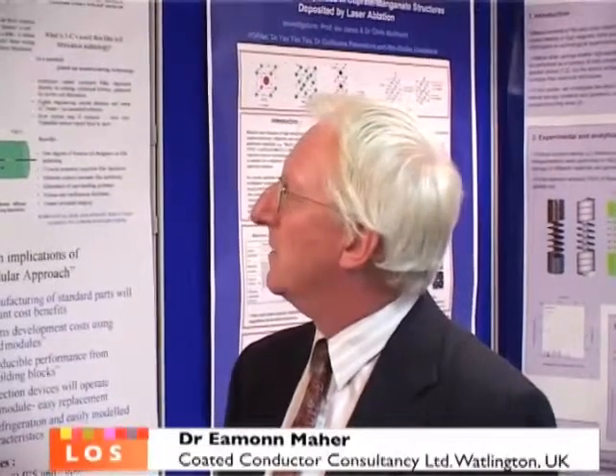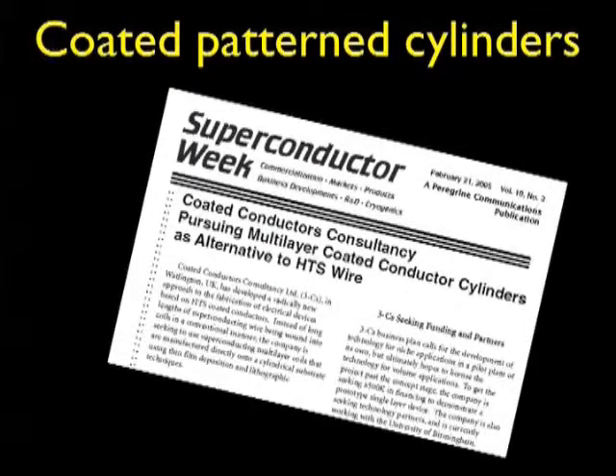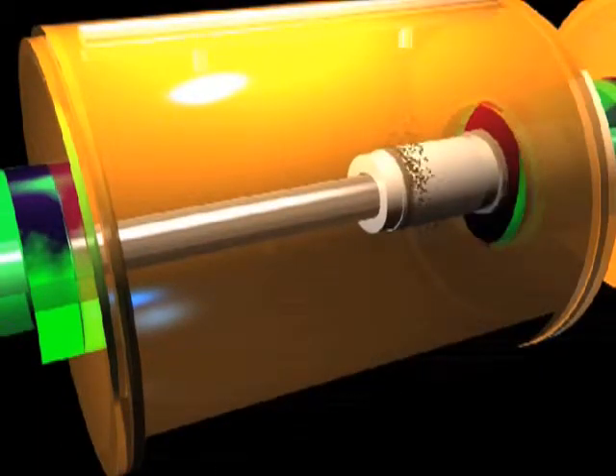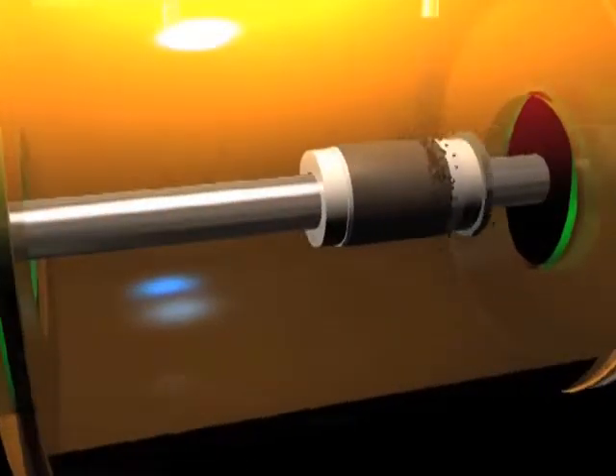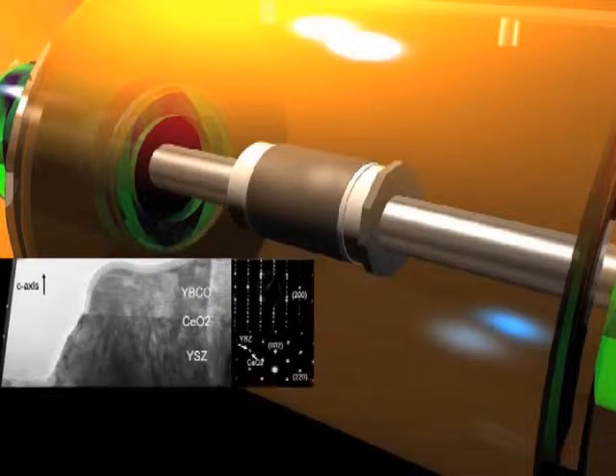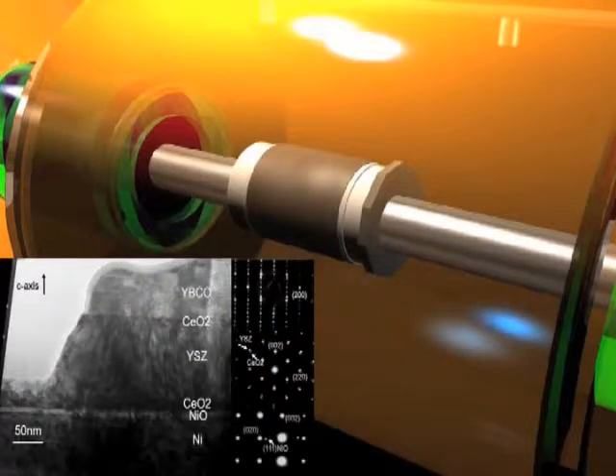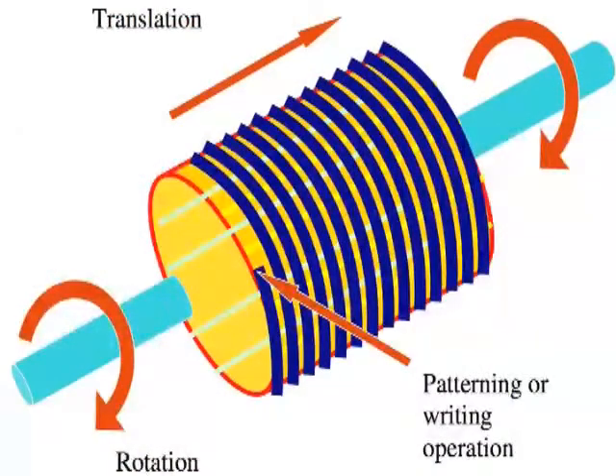For the last few years, people all around the world have been trying to fabricate long lengths of coated-conductor tape. Everybody realizes it has excellent performance, but nobody has fabricated very long lengths of it. What we're proposing here is, instead of trying to make long lengths of tape, we're actually depositing the various films on cylinders. The whole processing is done uniformly because of the coaxial cylindrical geometry, and then we pattern the films afterwards in order to make electrical machines of different types, all using essentially the same manufacturing technology.